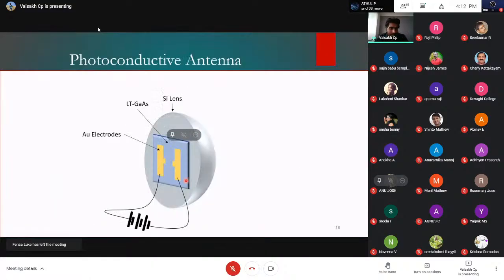This is an antenna. So there are gold electrodes attached on a low temperature grown gallium arsenide. The electrodes are biased, but this is such a bad conductor that there is absolutely no current flowing. The dark currents are probably on the order of picoamperes, and there's practically nothing happening here. It's just some voltage across this.